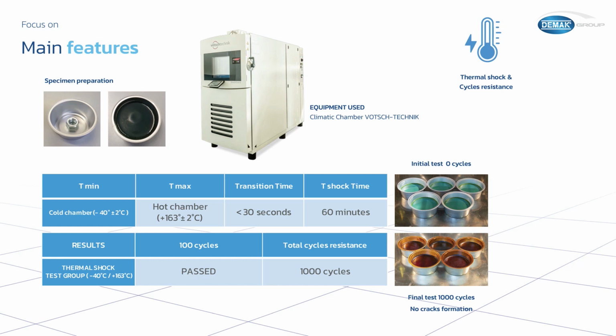The results are incredible. Not only did we arrive at 100 cycles, that is the minimum that we ask for the system, but we arrived at 1,000 cycles without any crack, and we stop at 1,000 because we need to use our chamber for other tests.